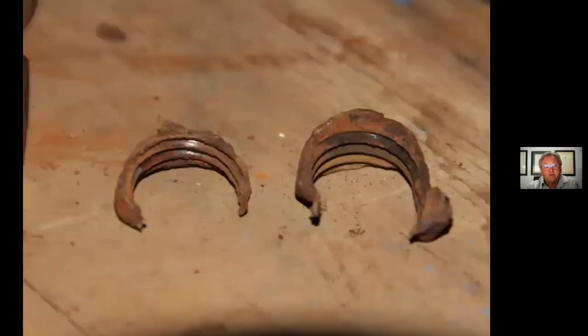Here's a similar situation. In this case, it led to an expensive failure of a valve, a $50,000 valve, because one of the main contributors was the incorrect nuts. There's the remains of the nuts that we picked up on the bottom of the pipe that used mixed up stainless steel and carbon steel nuts. Carbon steel nuts corroded away, and the net result was that failed seal retaining ring.